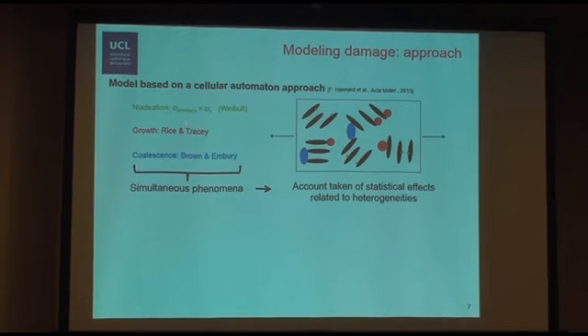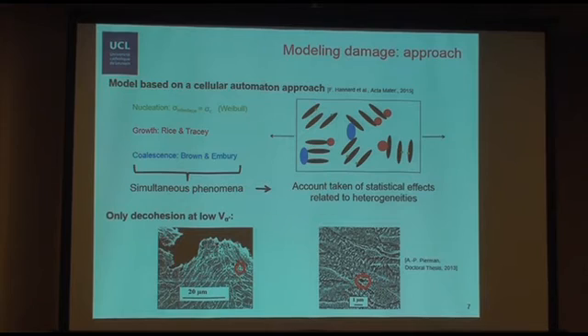The model is based on a limited number of simple equations. It's the attainment of a critical stress for nucleation, or actually it's a distribution of stresses, a Weibull law, another heterogeneity. It's Rice and Tracy for the growth, and Brown and Embury for the coalescence of the voids. This model actually has been developed for aluminums by Floriane, who's a colleague in the room, and it has been up to now using only decohesion for nucleation.